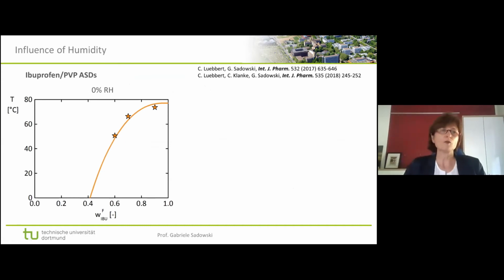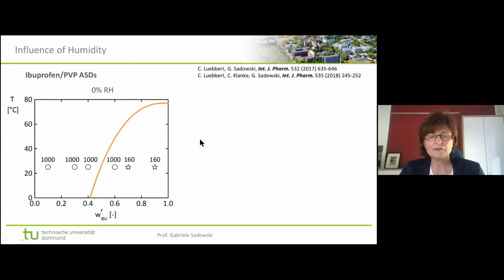This is another example where we have ibuprofen and PVP. This is again the solid liquid equilibrium line. Here you see the DSC measurements, which we have at high temperatures, but we would like to know what happens here at 25. This is a dry system, and this is the system which we use to fit the kij between the ibuprofen and the PVP. So the orange line here is the correlation. And then we predicted what would happen if we increase relative humidity, for example, to 75.